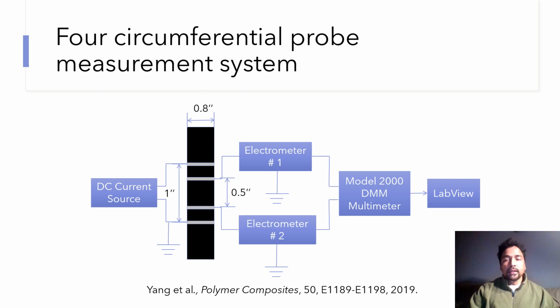Hence, we employed a Keithley instrumentation system, which is a high-resolution, highly accurate measurement system, where we supply a constant current through the outer probes, which are separated by 1 inch, and then we measure the voltage between the inner probes using a set of electrometers. These electrometers have high impedance, which prevents any current leakage. At the same time, they provide accurate voltage measurements when we are testing a high-resistance material like this. These two electrometers provide differential voltage to the digital multimeter, which is a Keithley model 2000. Later, we captured the voltage measurements in LabVIEW for data acquisition. The details of this instrumentation can be found in the reference below, in our paper published in Polymer Composites.